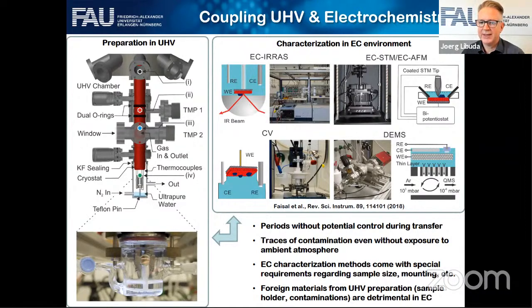If you look at these electrochemical in-situ characterization techniques, they all come with very different requirements regarding the sample size, quality, and so on. So you have to think about how to connect these, especially for every technique. One very important thing is, if you do this transfer, normally in UHV, you have foreign materials, sample holders, that you definitely don't want to have in the electrolyte. That's why we use this technique where you only use the crystal and not the sample holder, because you don't want the sample holder made of various materials to be in contact with the electrolyte.